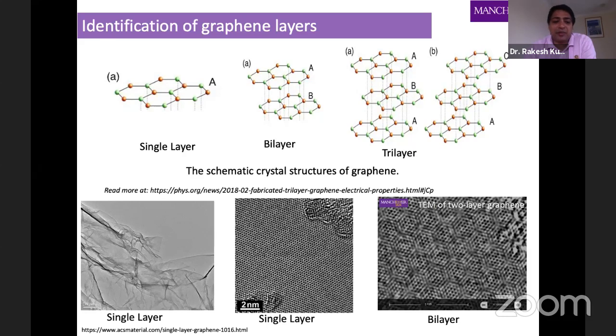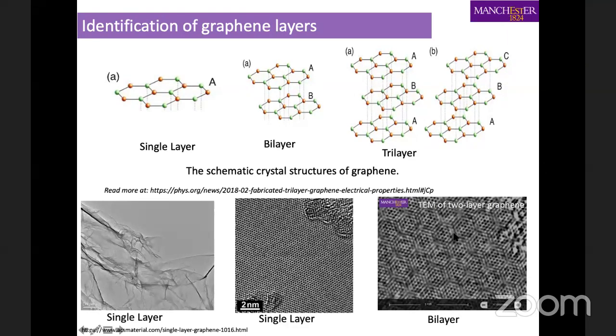What you see in the picture on the bottom left is single layer graphene on a silicon oxide surface. And in the middle picture in the bottom row, you see a TEM image, and you can easily see these honeycomb shaped carbon atoms connected along the sheet. A bilayer picture would be different than a single layer. You can see an impression of hexagonally connected carbon film.